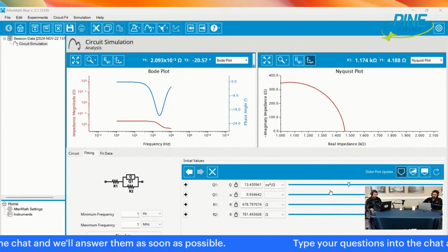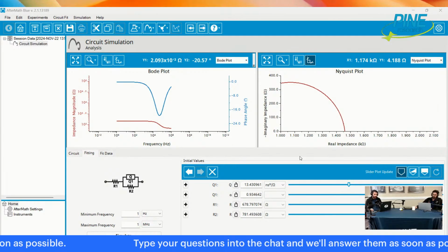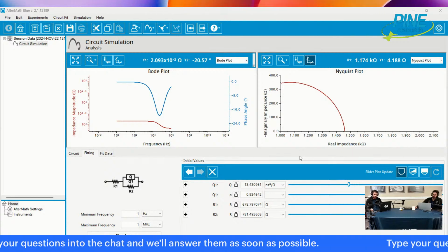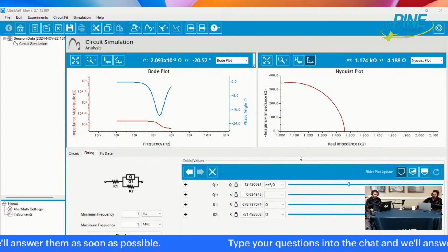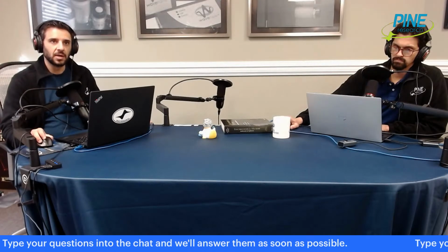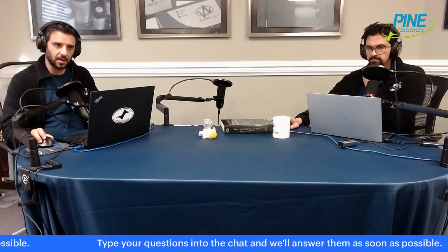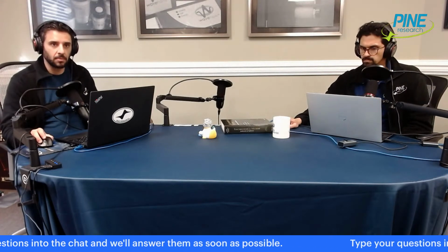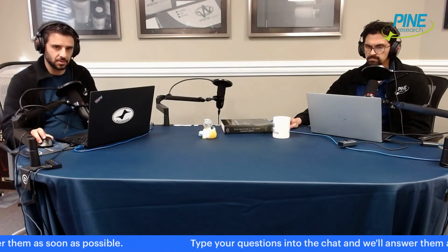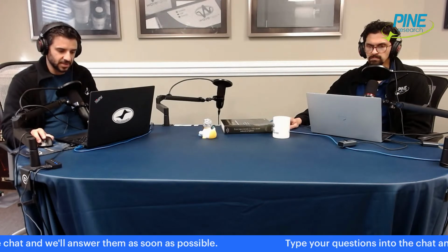So in summary, I can't answer why per se. You have some material, you've charged it with hydrogen. I don't know if I can answer perfectly well why charging with hydrogen leads to that. Obviously, something about the morphology, something about, I don't know, XYZ property of your material after charging with hydrogen, or this process that you've done, has led potentially, I would say, to a higher resistance, higher impedance, which might be a degradation of some sort. I don't know. Hydrogen can cause cracking in structures. Maybe that's what it is. Just a guess. Or again, it has a lower capacitance. So again, I don't really even know how or why.